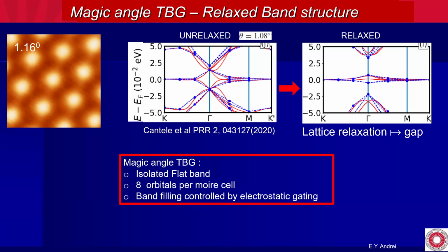Okay, of course, you have 8 orbitals per Moiré cell, 2 for spins, 2 for K-valley, and 2 for sublattice. If you gate the sample with a gate voltage, you can throw in electrons and change the Fermi level and bring it into the flat band or bring it outside of the flat band. So you can explore this band structure because the electronic density is so small that with a small gate voltage, you can actually change the Fermi level by a little bit, as opposed to what would happen if you have a regular metal.